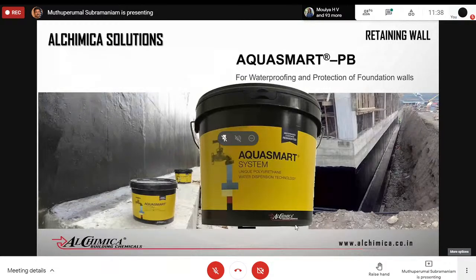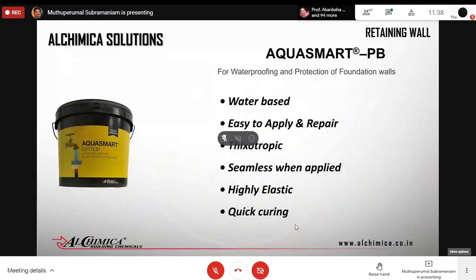So the retaining wall remains wet for a minimum of 70 to 80% of the construction period. So when we apply waterproofing treatment on the retaining wall, the liquid applied system that we are recommending should have the ability to stick on the wet surface. So this particular product, water-based polyurethane or solvent-free polyurethane, is ideally recommended for retaining walls even under wet conditions. It's a very thixotropic product, so the thickness can be developed. There's no need for multiple coats to develop thickness. It is elastic and quick curing. This is also another important property.